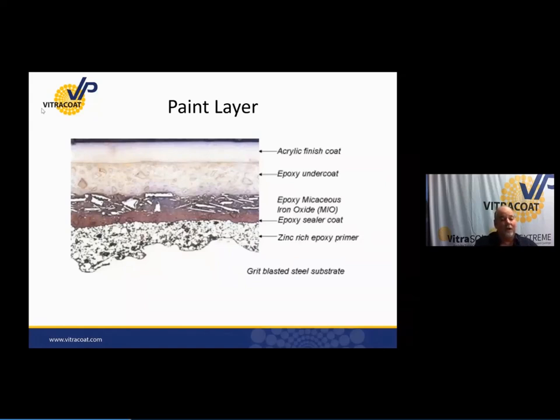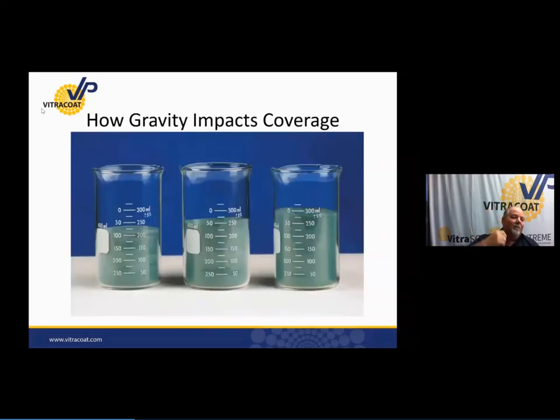Now, powders, they don't have a lot of evaporation after it's coated, right? You're spraying it in the dry form. You can only put so much zinc in it. And 65, 70, 75% is probably going to be about the top you're going to get in a powder coating before it becomes so heavy it can't even be sprayed or fluidized. You see, if I've only got a small amount of zinc, these are 3 different coatings. Each of them looks the same. They don't perform the same, but they look the same. The one on the right has no zinc at all.